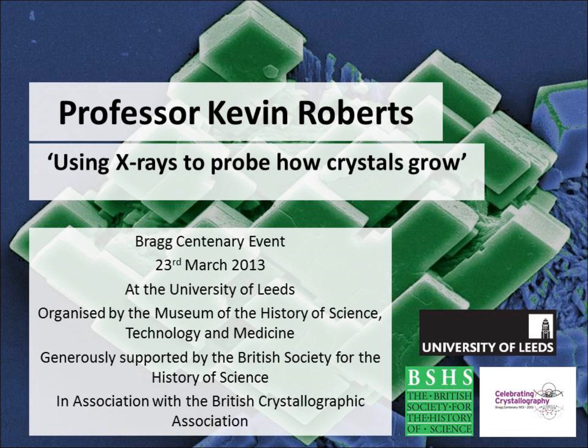This material has a fantastic cleavage plane. So if you squeeze the crystal, you can break it off. Just rather like if you've looked at mica, you can peel the crystals off. And so it's very, very weak in this basal plane. And you see all these lovely dislocations. And these are the growth dislocations that are enabling these faces to grow. A little imperfection here, a big bundle of dislocations making the crystal grow fast.